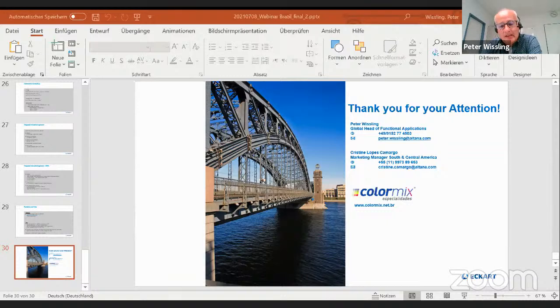No, typically we recommend orientation leveling agents when aluminum flakes are being used in order to improve on the flake orientation, the flake alignment in the paint film. For zinc flake, that is not necessary. The reason is that the amount of zinc flakes is substantially higher in a formulation, as mentioned, 35%. And the second reason is we do not recommend to use these. They have negative impact on the corrosion protective performance of the paint system. So no, we would not recommend to use orientation leveling agents.